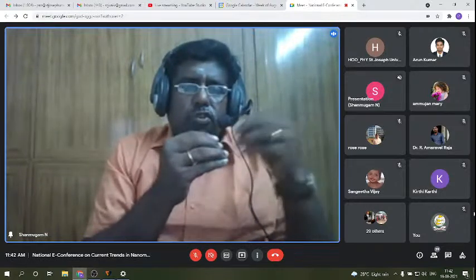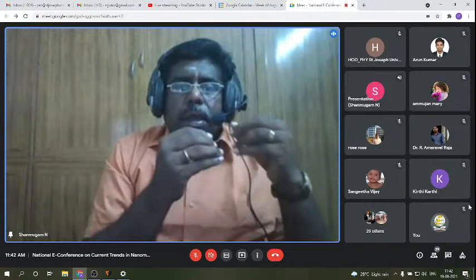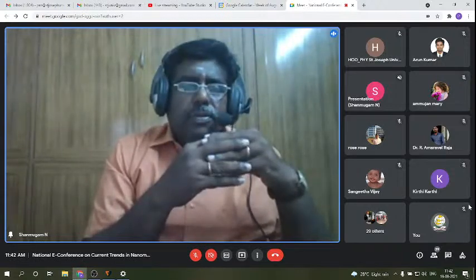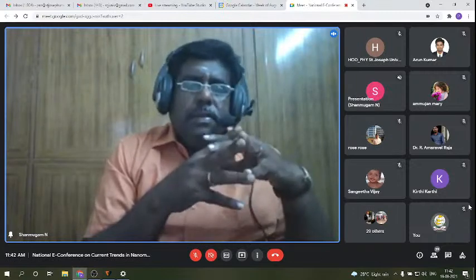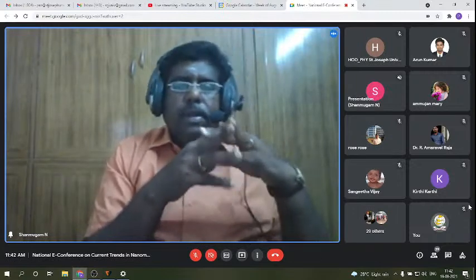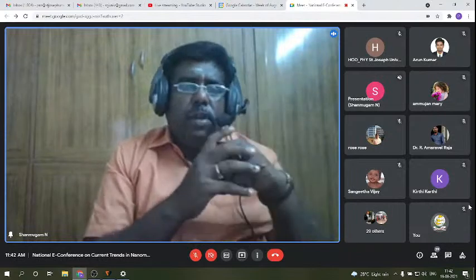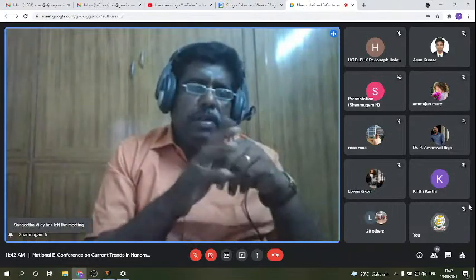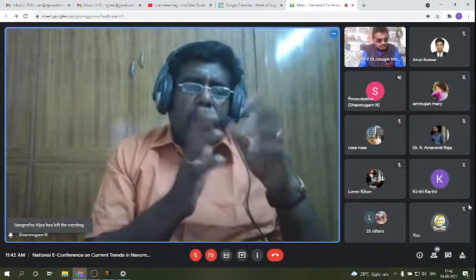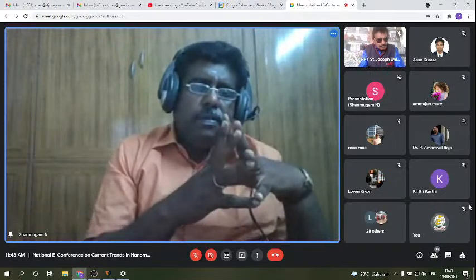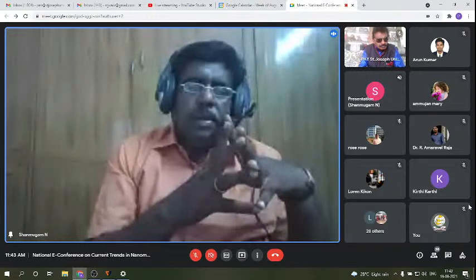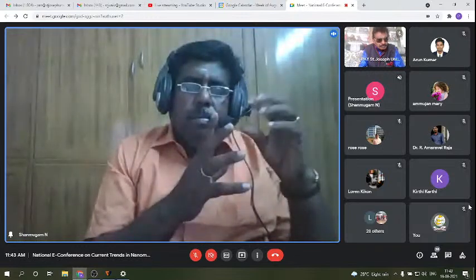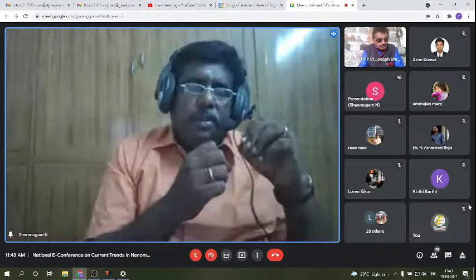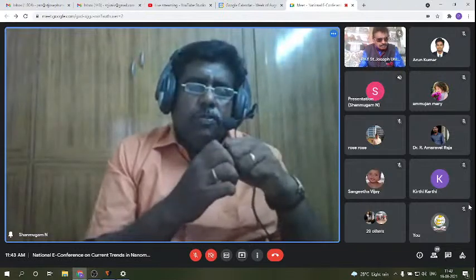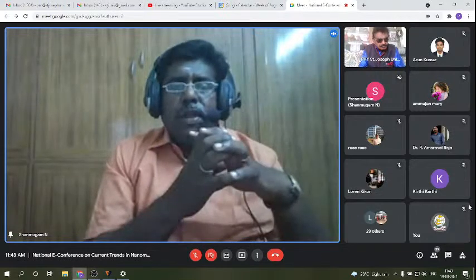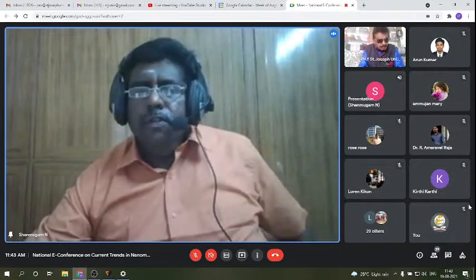When ZnO is doped with an appropriate amount of dopant atoms, its catalytic activity is increased. Firstly, the impurity atoms hinder the electron-hole recombination. The role of the impurity in ZnO is that it doesn't allow the recombination process to take place in the photogenerated charge carriers. Because they act as trapping sites, they trap the charge carriers separately, so that the recombination of electrons and holes is highly forbidden.